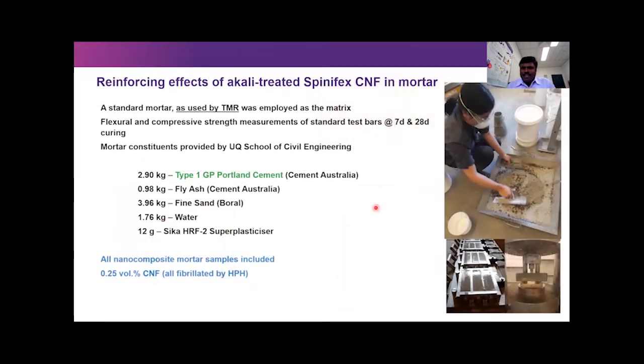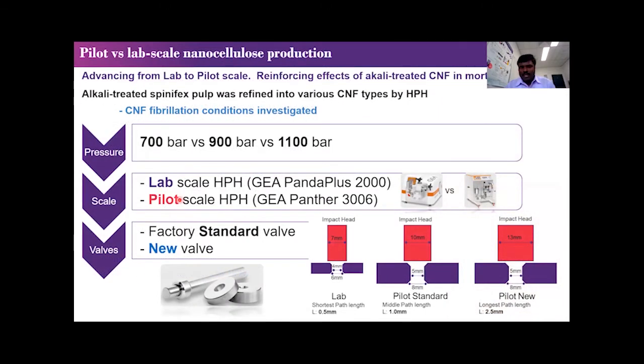And then we were trying to scale up this process. Okay, so then we tried this at large scale. You have the recipe here, which is cement, fly ash, fine sand, and water plus plasticizer. We added only 0.25 volume percentage of CNF in this.